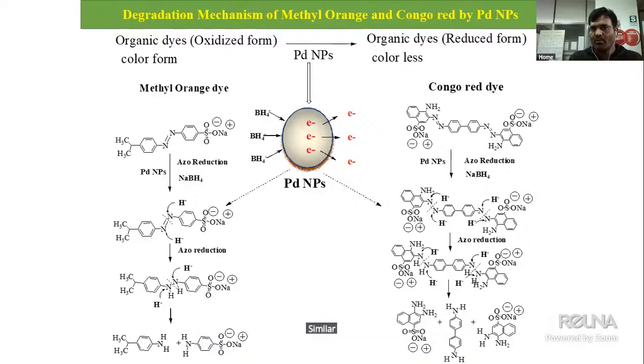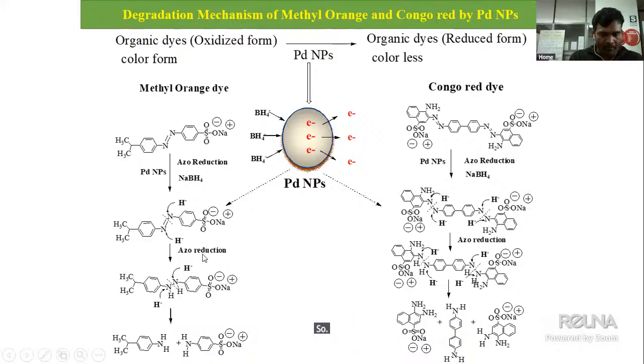In a similar way, the degradation of the azo dye in the presence of catalyst is proposed. For methyl orange, we propose the mechanism. That means the hydride ion, in the presence of catalyst, is absorbed. Then ultimately it diminishes the activation energy barrier. So between the dye molecules and sodium borohydride, the catalyst acts as a mediator. It enables the transfer of the hydride ion.